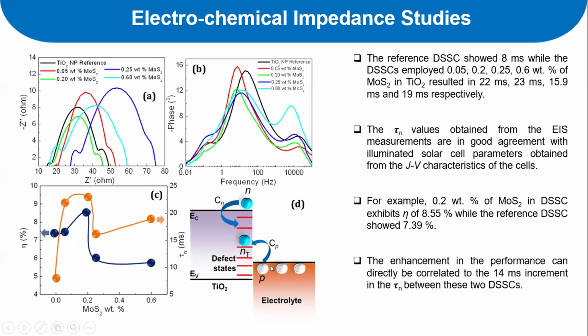So basically, figure D is the entire scenario. We have an electron acceptor in which the 2D layer semiconductor is coated, and then we have electrolyte, which is a hole transport layer. So it forms a p-n junction. Once we have the photogenerated electron in the conduction band of the titanium dioxide, it is supposed to be transported to the electrode, which is a transparent conductor in this particular case. And before it gets transported to the electron collector, which is the FTO, we have surface states in the electron acceptor, which efficiently capture the electrons, and then they get trapped in the defect states in the band gap of the material.